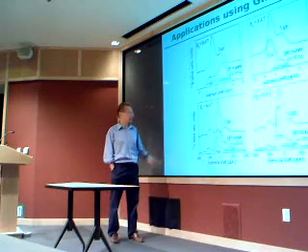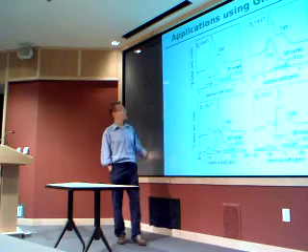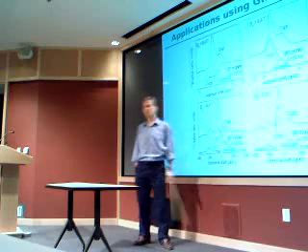And then, since I'm talking about NMR, here's the simulation for NMR. On the left-hand side, first for the boron and then for the oxygen nuclei, the NMR signal, and here's the chemical shift. Now we have a glass, so we have a distribution of chemical shifts, and you have some characteristic peaks. If you look, for example, here, this is the calculated spectrum with the small fraction of boroxol rings. It doesn't correspond very well to experiments, whereas it corresponds much better, not perfect, but still much better, both for boron and oxygen, with the high fraction of boroxol rings.